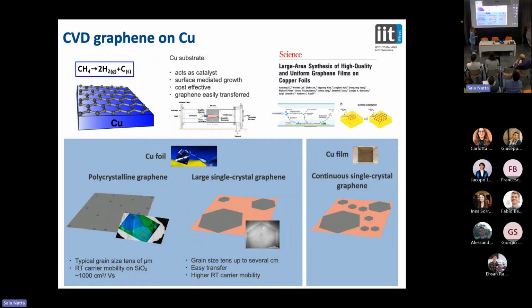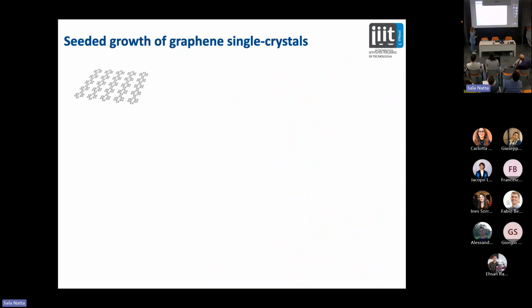So something IIT did, so my group did, and it was actually pretty successful, I will just jump because it's too boring, is to define the points of nucleation. It's nothing genius, okay, big discovery, big idea. But we were the first ones to do it very, very well. That means putting some seeds on the copper, and we use chromium because it survives up to 1070, that's the melting point of copper, but that's also the ideal temperature to really grow good quality graphene. We make it in a way that these seeds act as nucleation points, and then we grow our arrays.